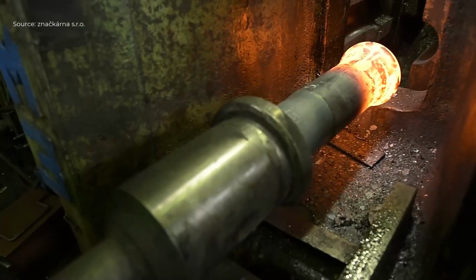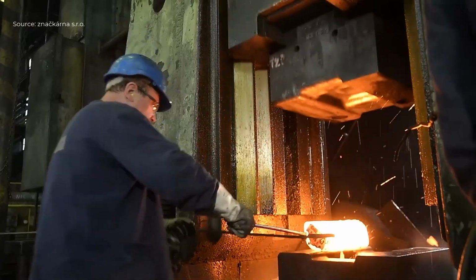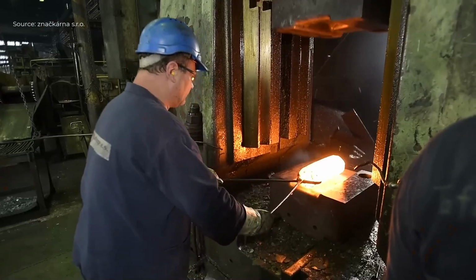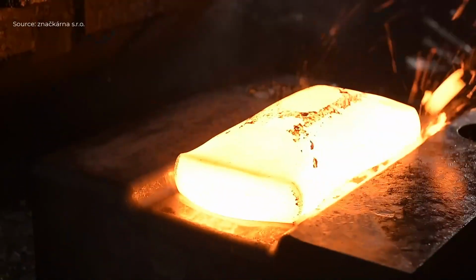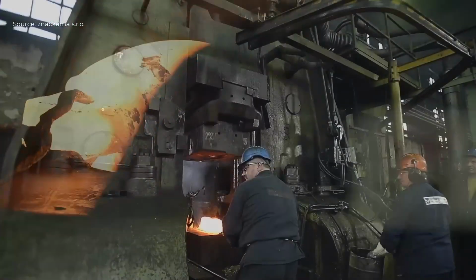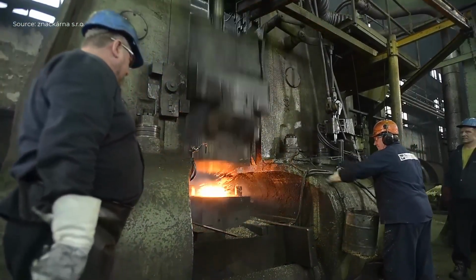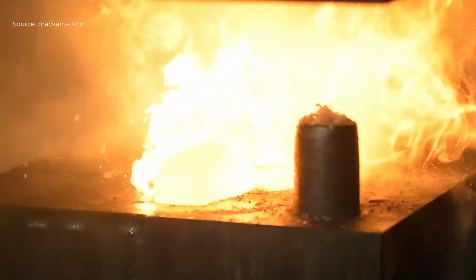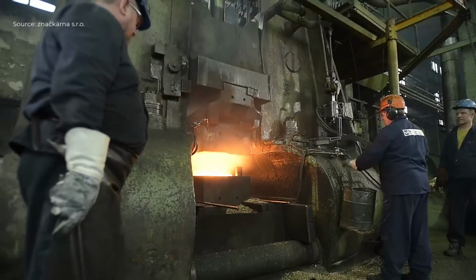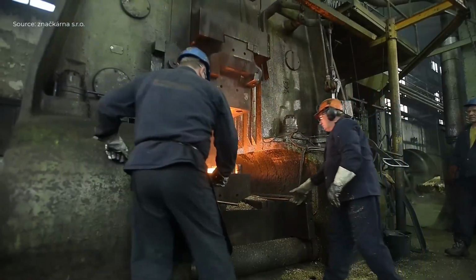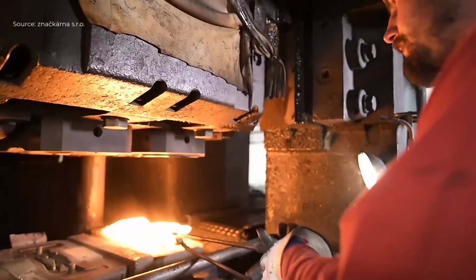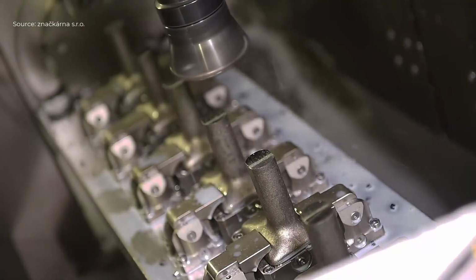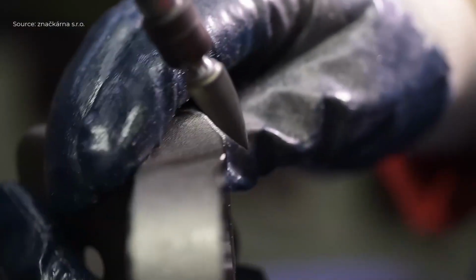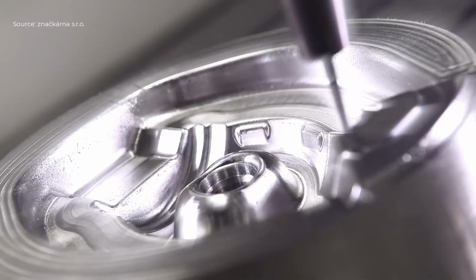Closed die forging, the hallmark, involves placing the heated billet into precision machined die cavities that reflect the final component shape. The dies, typically made from high-strength tool steel such as H13, are mounted on hydraulic presses or drop hammers that exert forces of 5,000 to 50,000 kilonewtons. This process is used for complex parts such as crankshafts, connecting rods, and gear blanks, in which steel is flowed to fill a die cavity under high pressure, achieving tight tolerances of up to plus or minus 0.5 millimeters. The die is lubricated with a graphite or water-based lubricant to reduce friction and prevent sticking, ensuring smooth extrusion of the forged part.